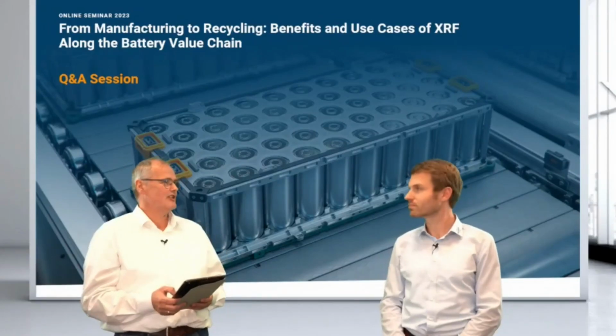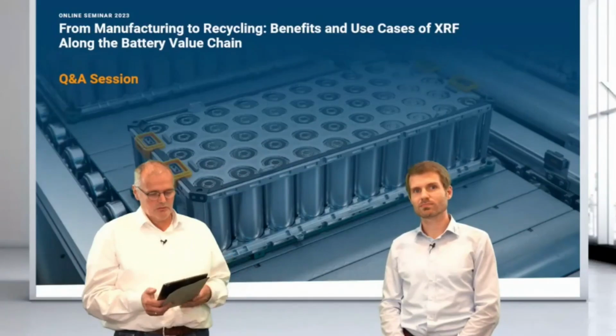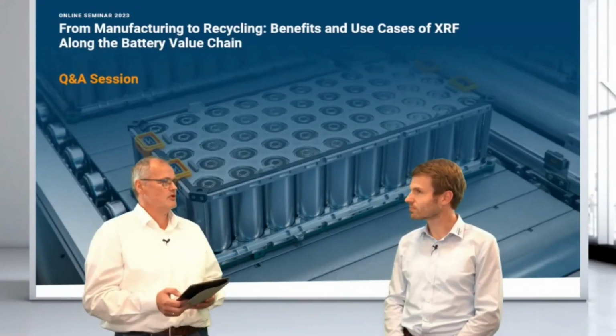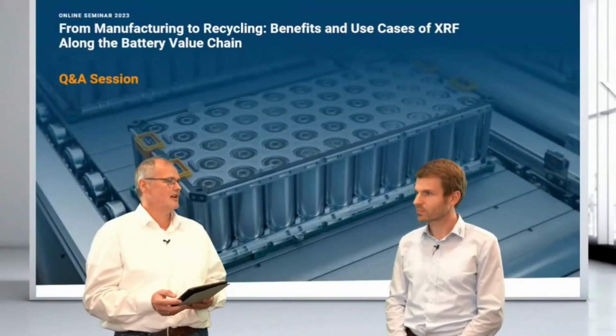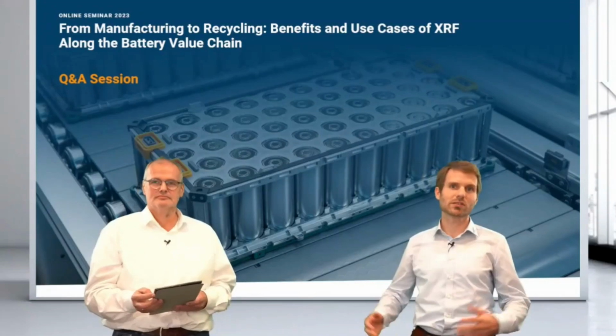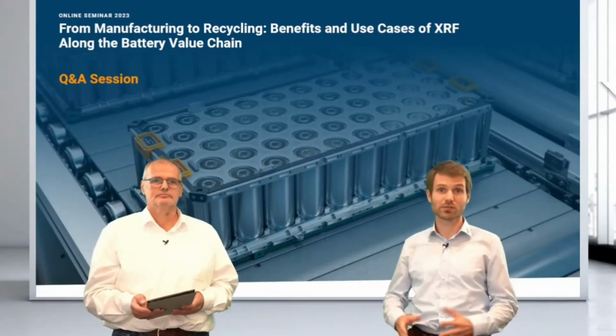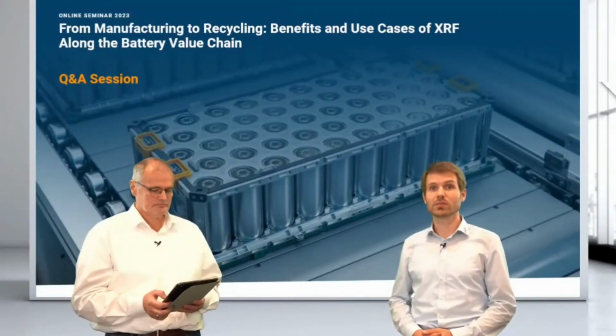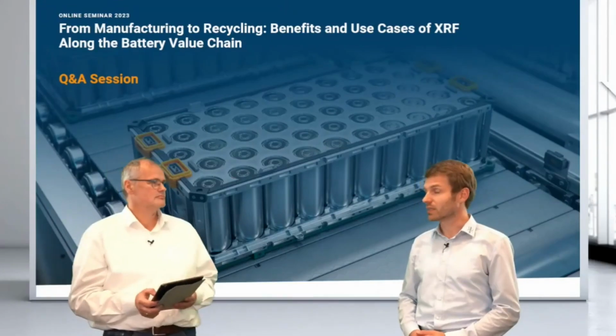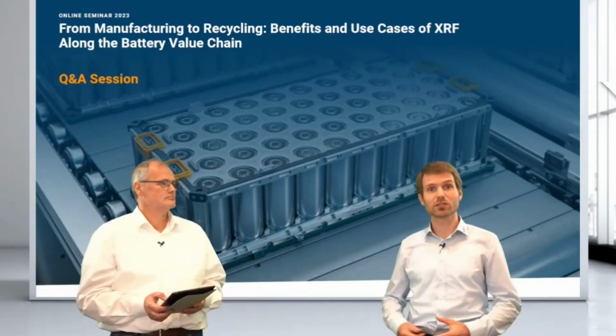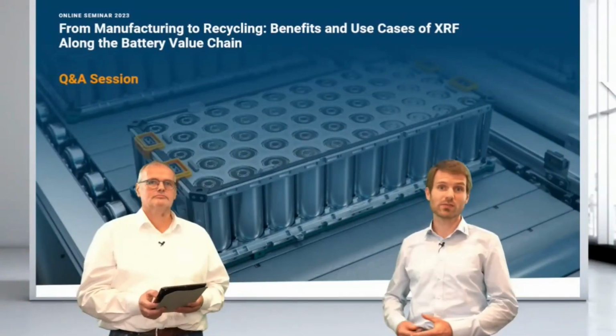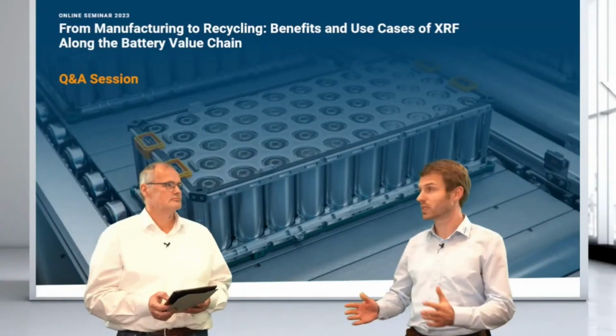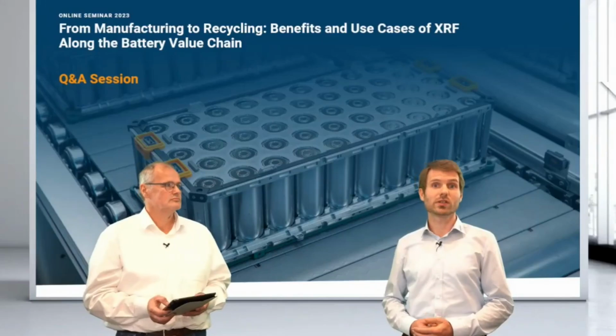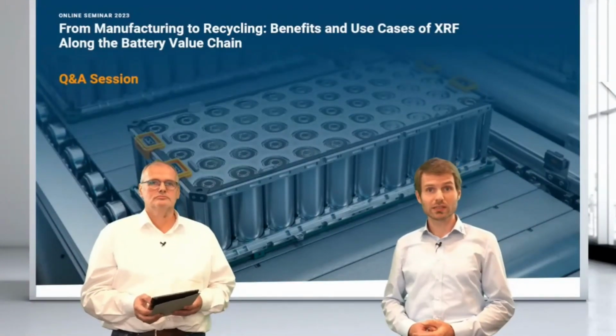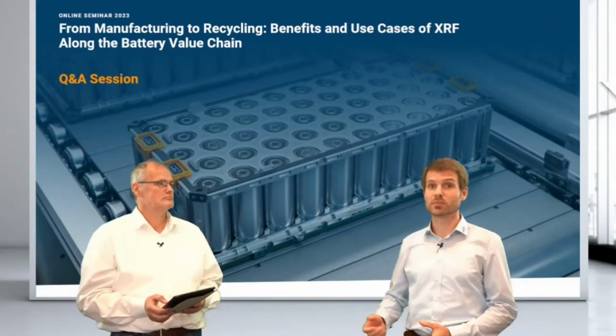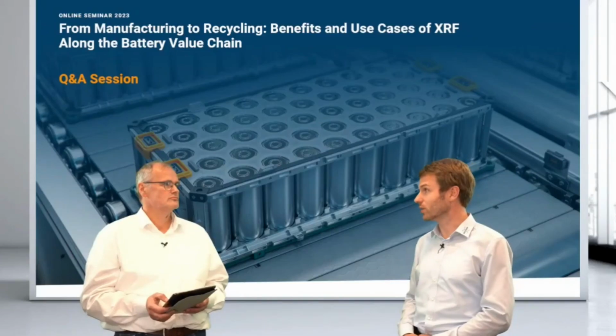Let's start with an easy one, Adrian. How would you determine whether you are using energy dispersive or wavelength dispersive XRF for battery applications? One of the factors is, of course, how much performance you need in terms of trace element sensitivity. But another one can be, especially when you're looking into lighter elements such as fluorine or sodium, especially to the lower concentrations, this is typically where you benefit significantly from a wavelength dispersive system. You have a better peak separation, a better signal to noise ratio. So for instance, if you want to measure residual fluorine in samples or sodium, this could be a good task for the S8 Tiger or S6 Jaguar.